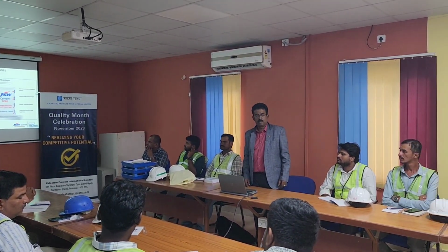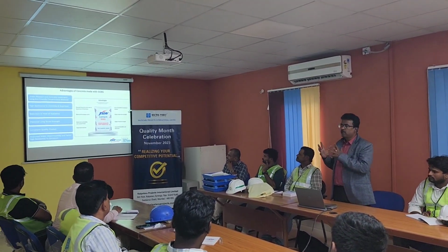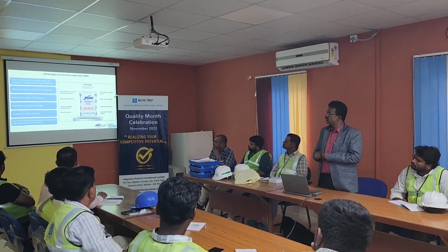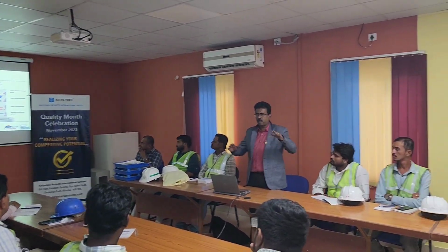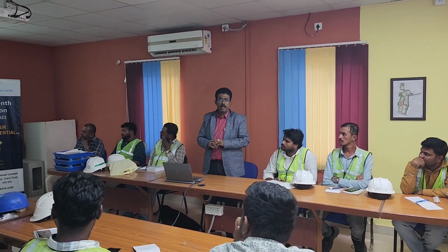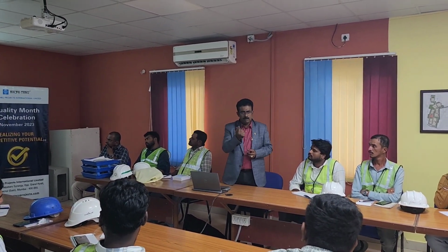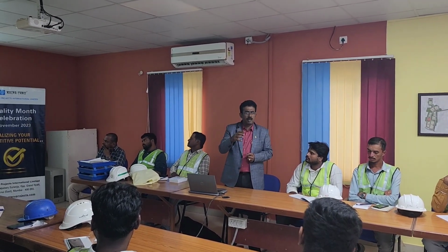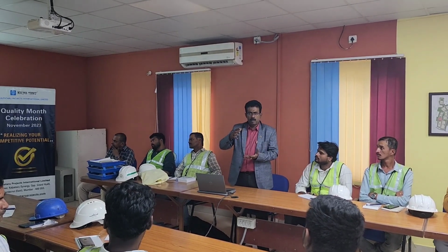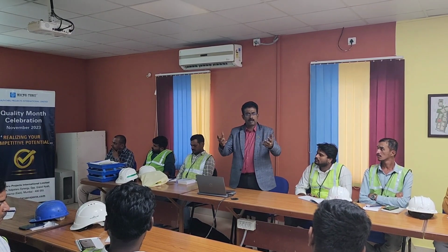Coming to the advantages of GGBS, there are so many. It's a green, eco-friendly product, and it is resistant to sulfates and chloride. The heat of hydration will come down, especially in a raft foundation when you are making a 1 meter, 2 meter, 3 meter raft. There, rather than the strength of the concrete, durability is very important: controlling the temperature of the concrete, because when you make the concrete, the central body will get heated up to 75, 80, 90 degrees centigrade, because the exothermic reaction liberates heat.